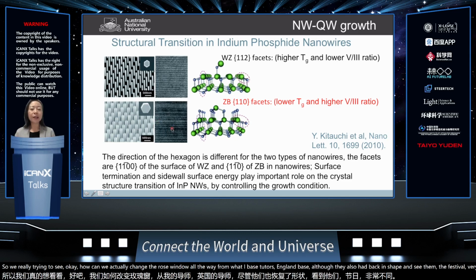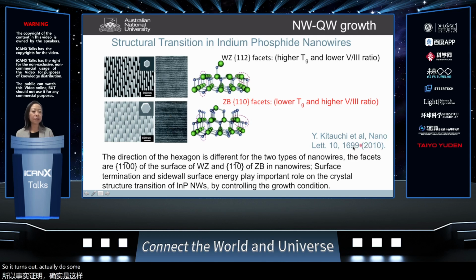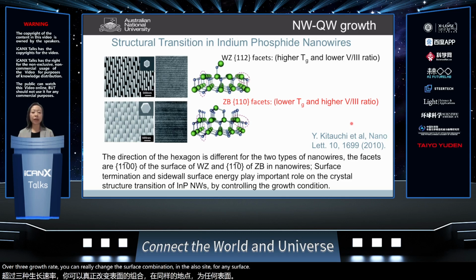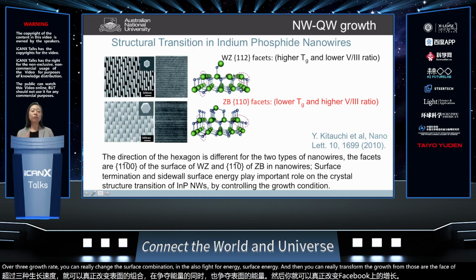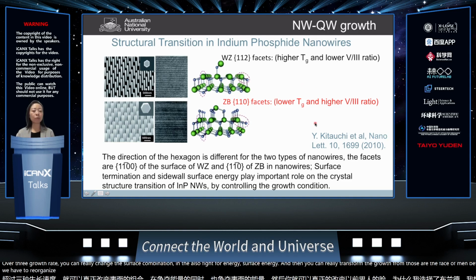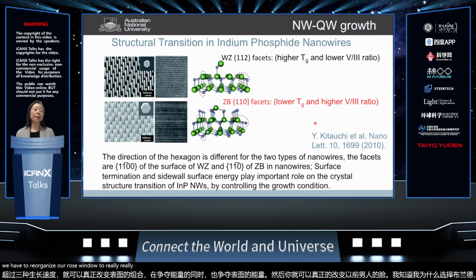It turns out the Japanese group has already done a very nice study in 2010, and demonstrated that if you change the growth temperature and the V/III ratio, you can really change the surface termination, also the surface energy, and then you can really transform the growth from a Wurtzite nanowire to a zinc blende nanowire. So basically, we have to re-optimize our growth window to really achieve a zinc blende based indium phosphide.